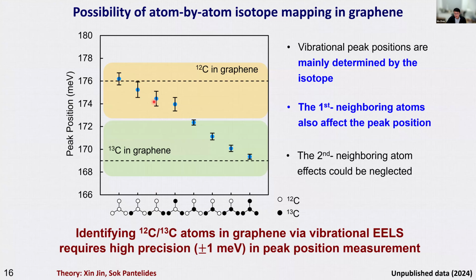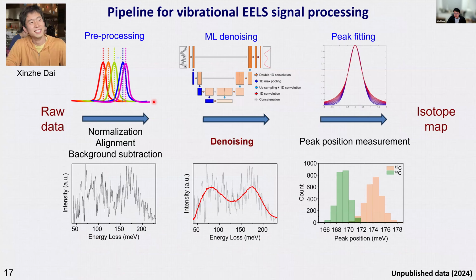And the second question is related to the accuracy, how reliably you can measure this peak position. You can see that the energy resolution in this case is still about 10 milli electron volt. But the accuracy with which you can identify the peak position is related to the signal to noise ratio. In fact, there's a question from the audience here just about that. At these scales, how do you manage noise and extract reliable vibrational frequencies from these data?